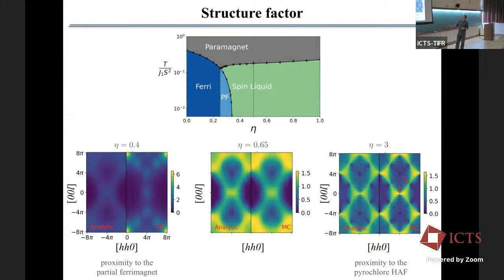Now, if you go to eta equals 3, so it's way beyond this. Eta equals 3 means that J2 is 3 times bigger than J1. So the couplings that matter are the pyrochlore couplings. That means that in this limit, you have the Heisenberg pyrochlore antiferromagnet with a central spin, which is almost uncorrelated from the rest. And so here you recover the pinch points of the Heisenberg antiferromagnet because you are in the 3D Coulomb phase.